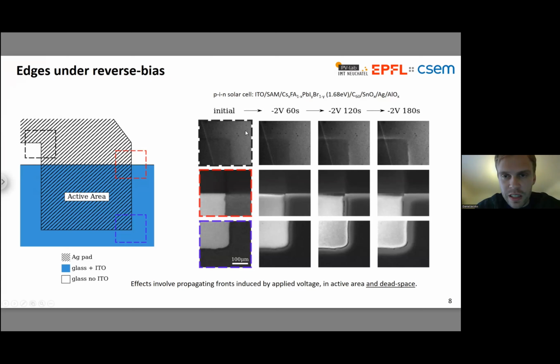And yeah, so we take images at intervals between these periods of reverse bias. And so what you can see is that at each of these regions, there's stuff happening. And in particular, we have propagating fronts at each of the boundaries shown here. And we also have activity occurring in the dead space, which is especially interesting and surprising.